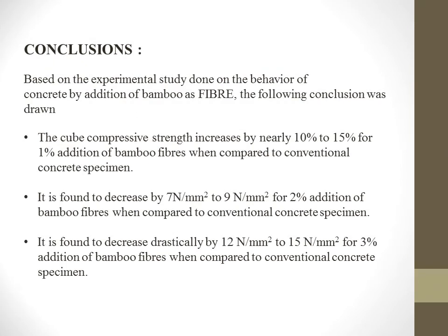Hence, we had come to the conclusions of our experimental study. I'd like to conclude by saying that the cube compression strength increases by nearly 10 to 15 percent with 1% addition of bamboo fibers, and it has been found to decrease by approximately 7 to 9 Newton per mm square for 2% addition of bamboo fibers, and it has also decreased drastically by 12 to 15 Newton per mm square for 3% addition of bamboo fibers.